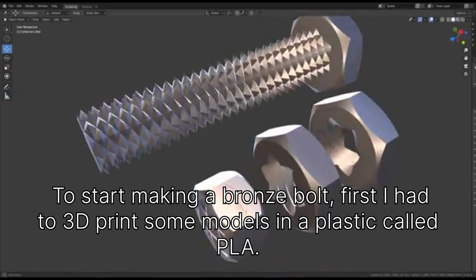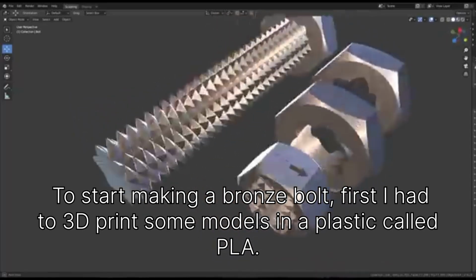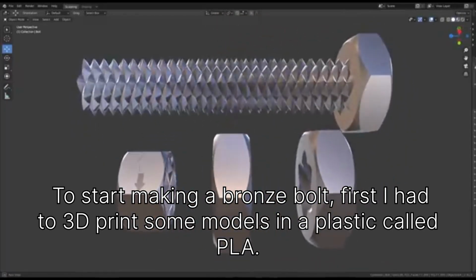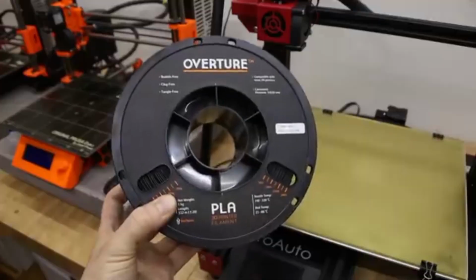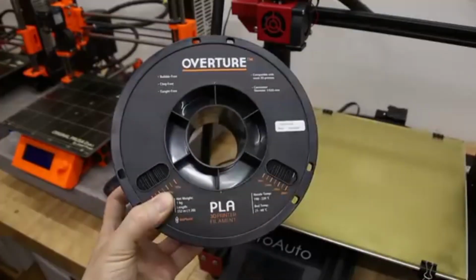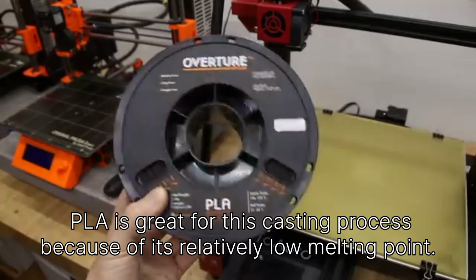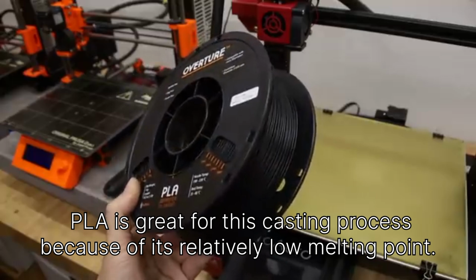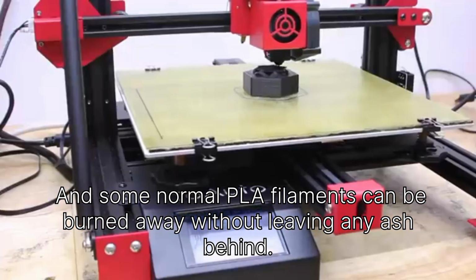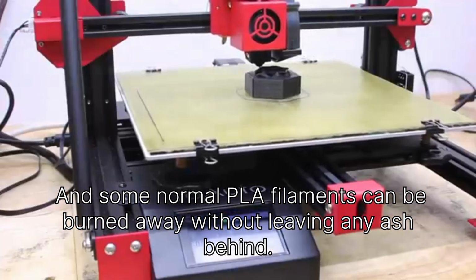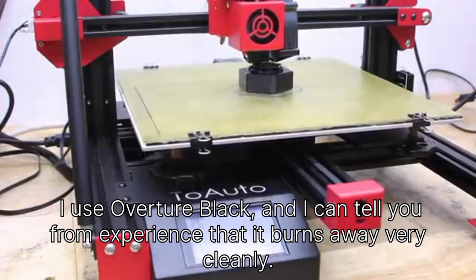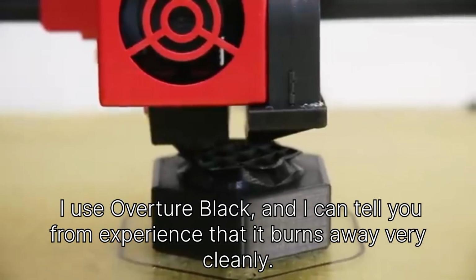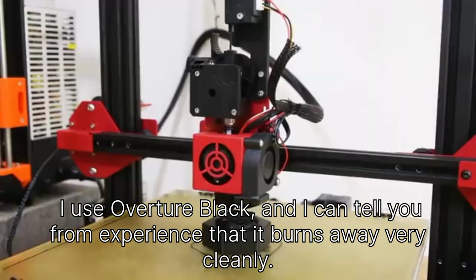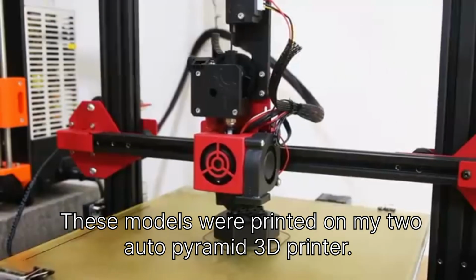To start making a bronze bolt, first I had to 3D print some models in a plastic called PLA. PLA is great for this casting process because of its relatively low melting point, and some normal PLA filaments can be burned away without leaving any ash behind. I use Overture Black, and I can tell you from experience that it burns away very cleanly.